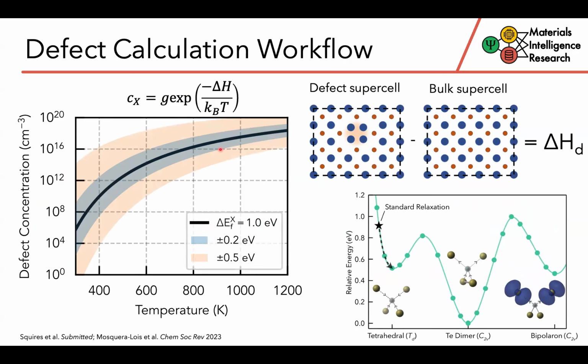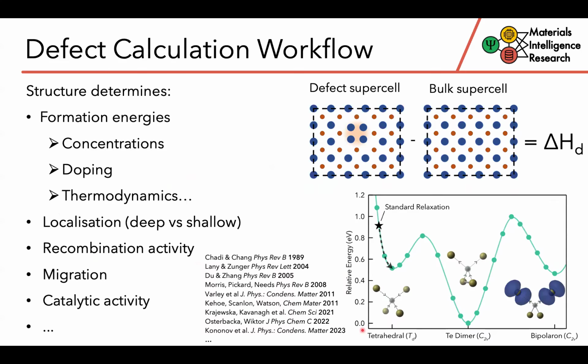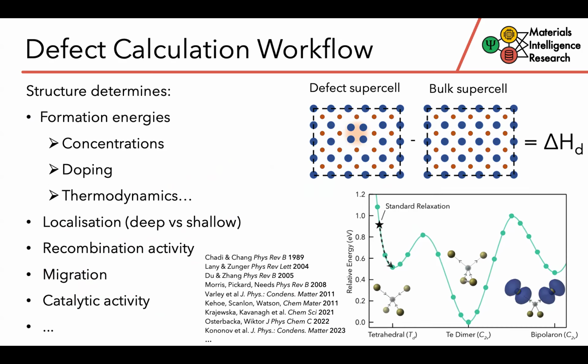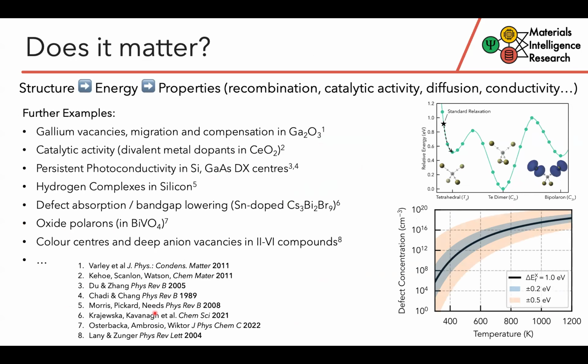Reminding ourselves of the fact that, as we saw earlier, this defect concentration is exponentially dependent on the formation energy. The higher formation energies that you will end up with if this happens can also lead to quite spurious predictions, where maybe you underestimate your defect concentration by several orders of magnitude. More generally, beyond formation energies and the derived properties there, such as, I said, concentrations, doping, thermodynamic effects, the defect structure is also important for things like localization, so whether the defect is a deep or a shallow type of defect, whether it has strong or weak recombination activity, migration behavior, catalytic activity, and more. So essentially, we can say that all properties of our defect are derived in some way from its geometry.